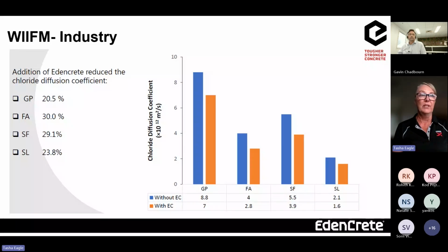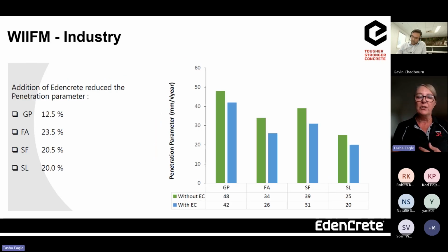So what you can actually see is different parameters, but we're seeing up to a 30% improvement or reduction in chloride ingress using the carbon nanotube technology when compared to just a standard 40 MPa mix design that's generally used out at the ports. And we did make sure that we were using a mix design that's relevant to the industry and what the asset owners have generally used. And then again, looking at the reduction in penetration. So this is another test that the university have done, Kod and the team. And you can see here, we're seeing a reduction as well with the use of the carbon nanotube technology in terms of the penetration into the concrete.